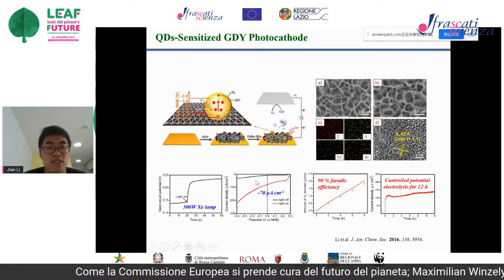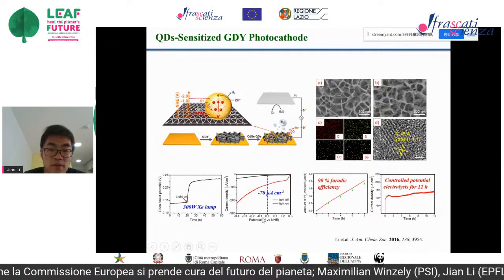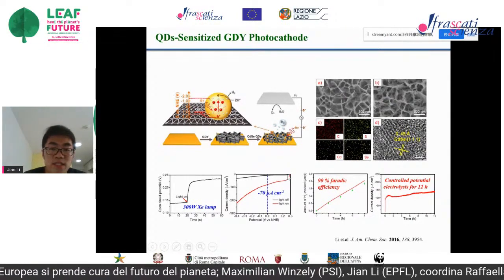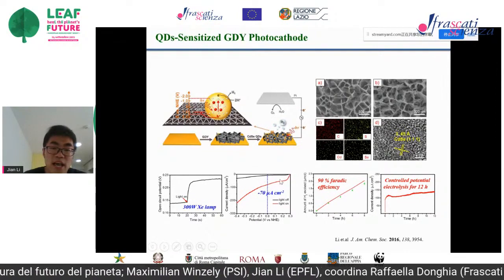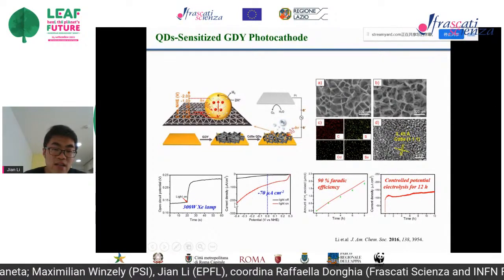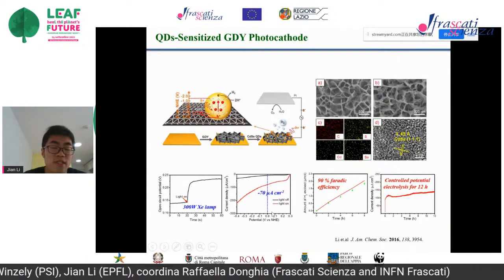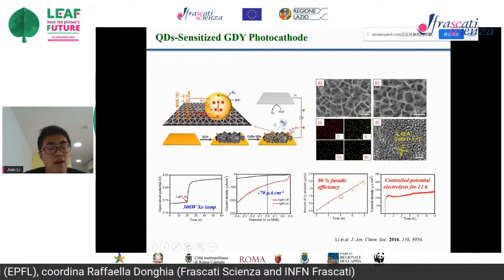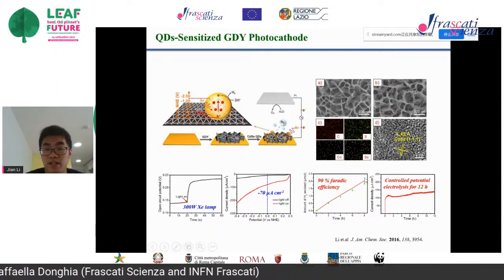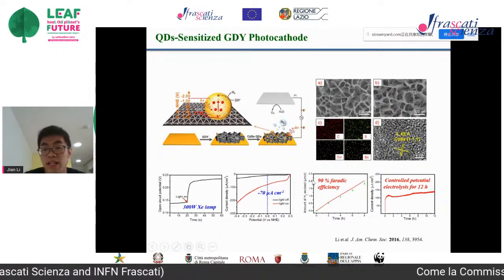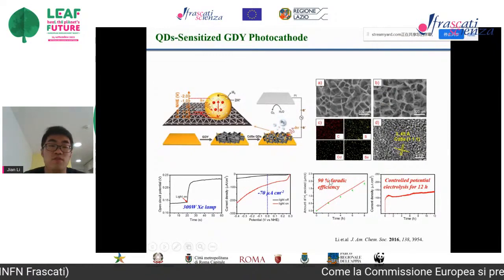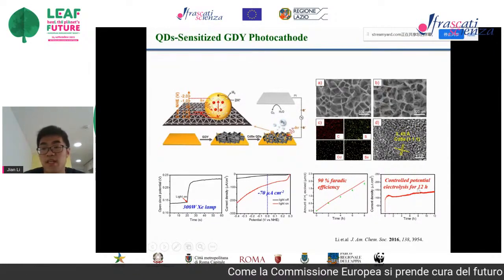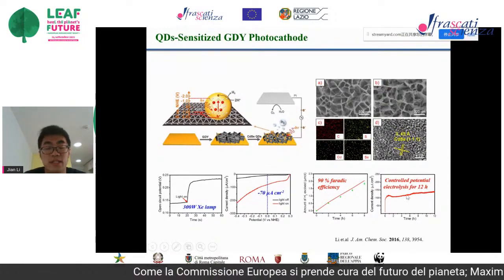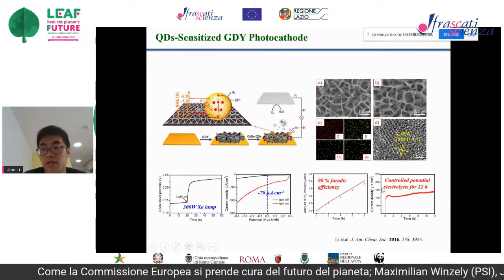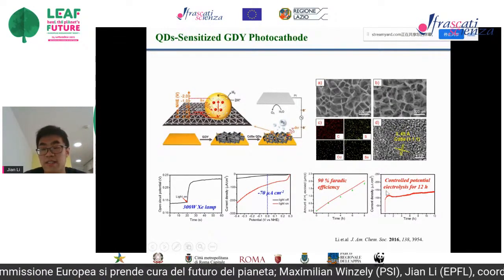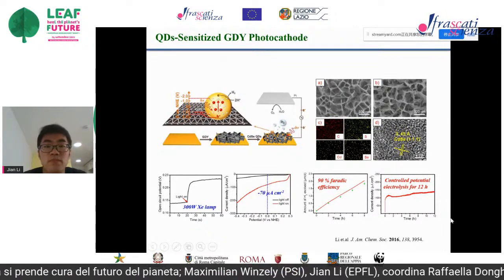And we also test the PEC cell activity. We can see this line is tested in dark, and when we shine light on, the photocurrent increases largely. We can also get a very good Faradaic efficiency for hydrogen, and 90% Faradaic efficiency for hydrogen can be obtained. It also shows very good stability. We can see that during a 12 hours test, it can keep stable.